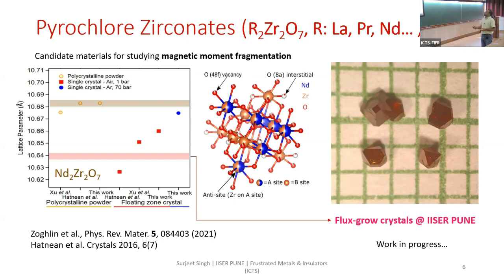So our interest here is to grow crystals of this material, but there are issues with respect to crystal growth of zirconates. First, the melting temperature is very high. You cannot reach that temperature by the ordinary float zone method that I showed you in the previous slide.